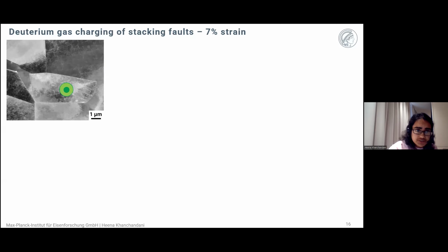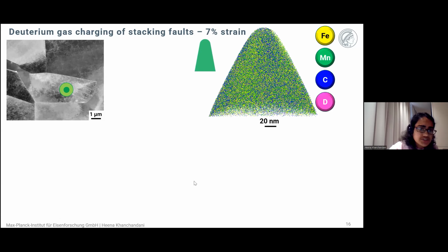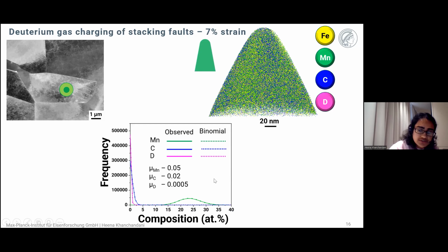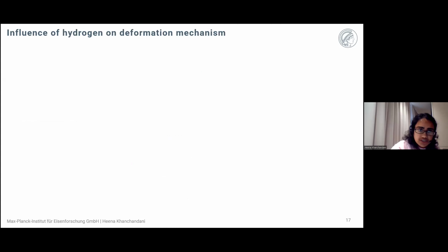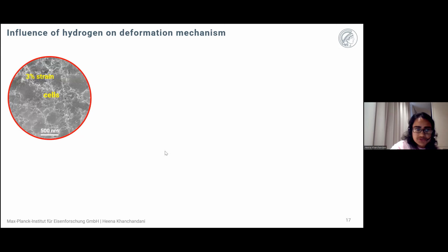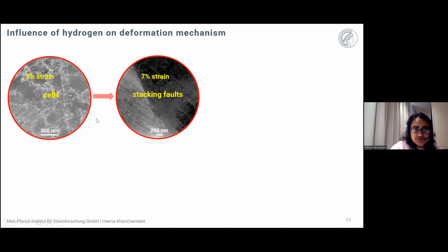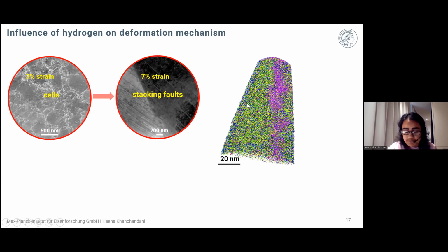So we prepared these samples from the region with stacking faults. And there too, we could not find any segregation of deuterium at any stacking faults. So this simply shows that there is a modification in the deformation mechanism by hydrogen, from the formation of dislocation cells to the formation of stacking faults. But hydrogen is not really segregated at these dislocation cells or stacking faults or at any of these dislocation structures. But its segregation at these grain boundaries modifies the deformation mechanism.